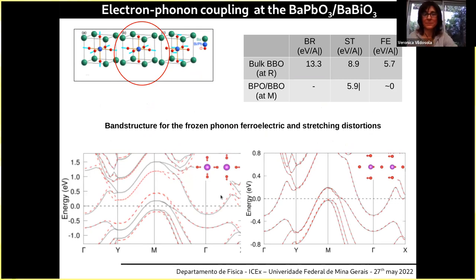This is because on one hand, you have the stretching mode here, and the doping here induces, this is the electron doping performed by lead that doesn't couple to the stretching mode, right? Because there is no shift in the electronic levels, but the S band coming from bismuth does couple to the stretching mode.